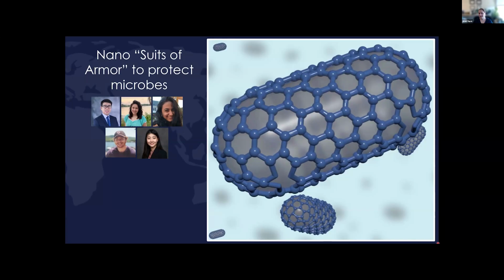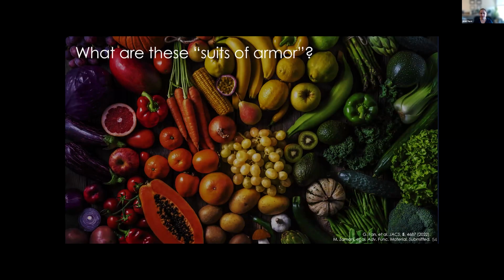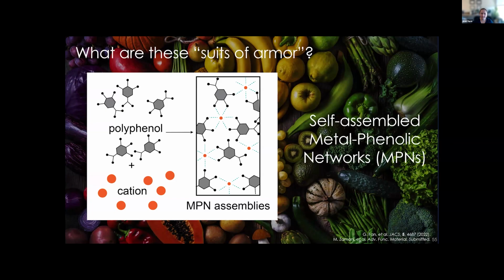Basically what we've been able to do is to take materials that self-assemble and use them to form these two-dimensional coatings on the outside of microbes. These coatings are made from food-grade components, polyphenols. These are things like tannins or green tea extract, combined with earth-abundant metal cations. So these are things that you'd find in your multivitamin, like iron or manganese. And when we mix those together, as long as there's a nucleation site, so something for that coating to start forming on, they form these two-dimensional networks very rapidly and readily, which we can see in this video.